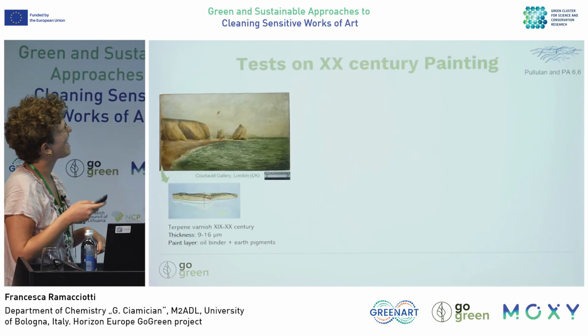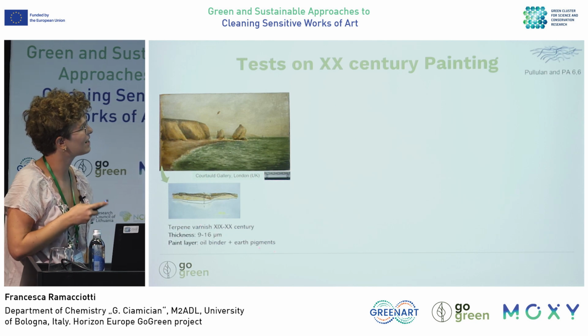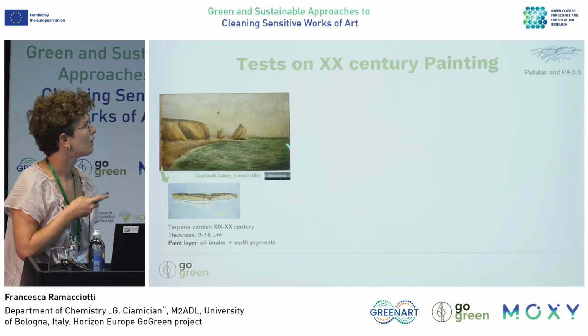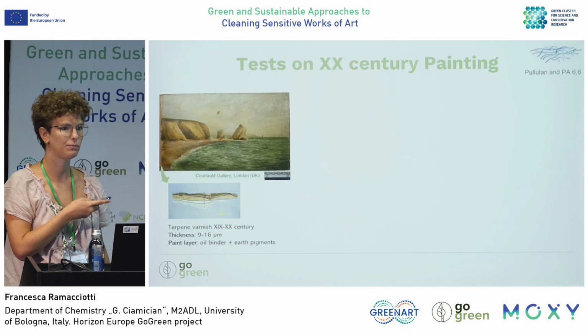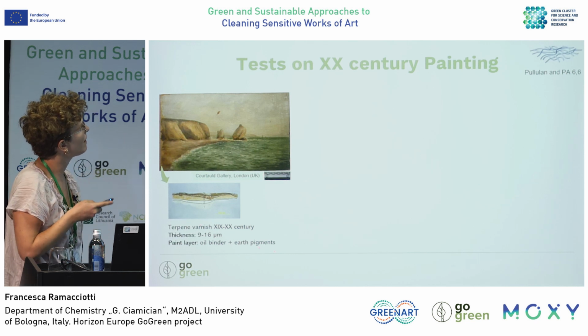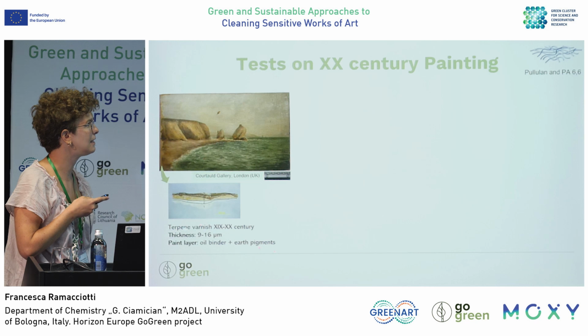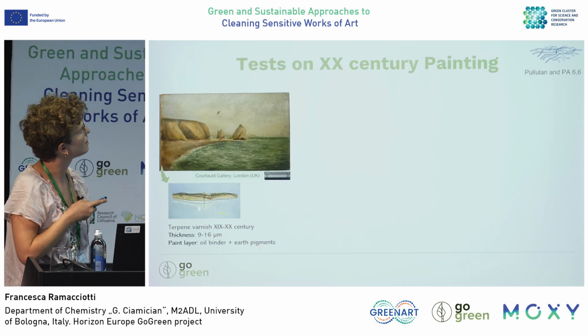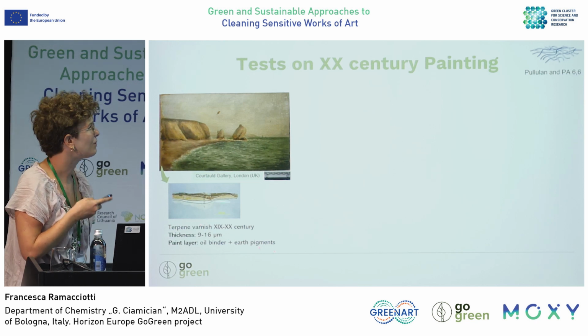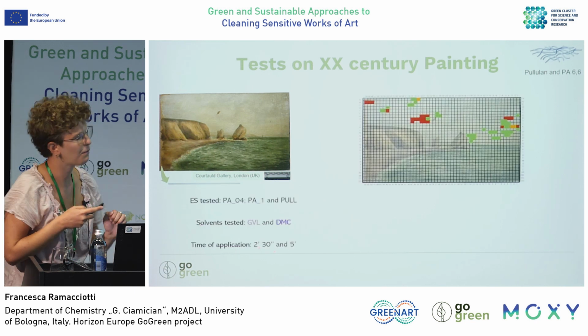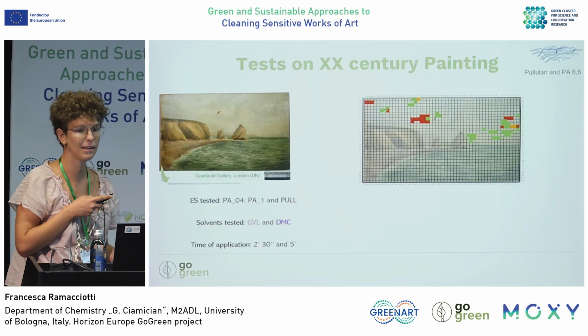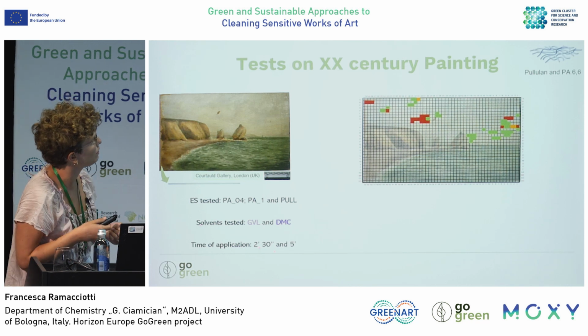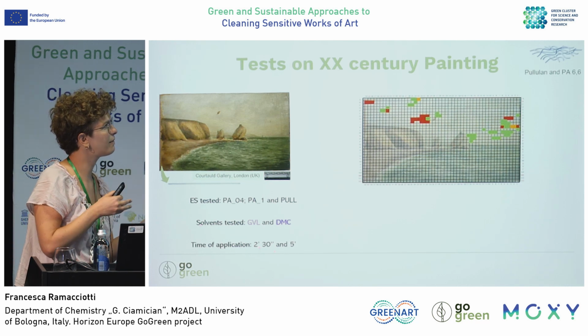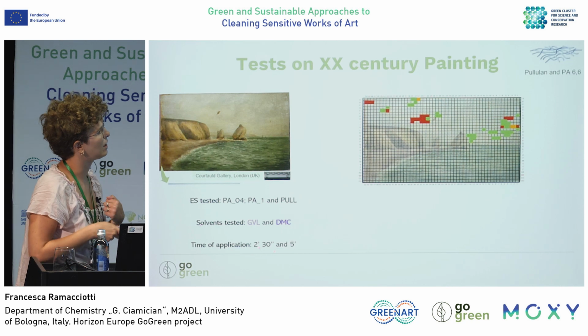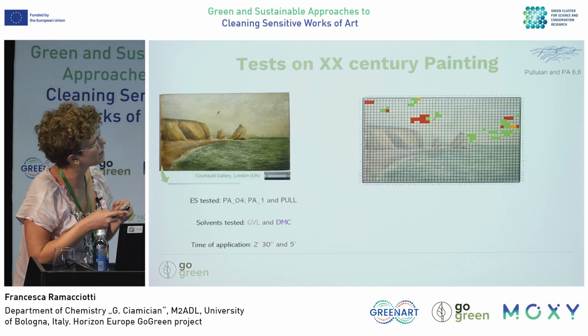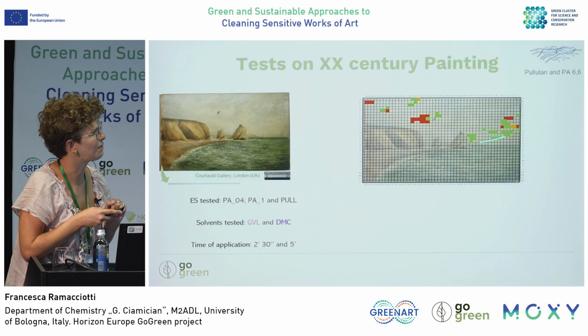And then coming to the testing on a historical case, the Courtauld Gallery, the Courtauld Institute of Art, which is a partner in the GoGreen project, provided us with a painting from the 19th, 20th century with yellowed damar varnish on top. And we tested both the polyamide with the small and intermediate pores and the pullulan with two different solvents, gamma valerolactone and dimethyl carbonate. And we tested different times of application, and here you have a grid of the initial tests that we performed.